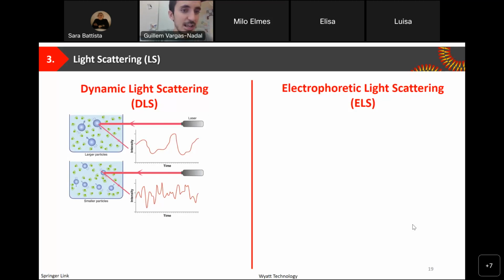First of all, in dynamic light scattering, or DLS, you have a laser with a specific wavelength, which impacts on your nanoparticles. And depending on the size of the nanoparticles, the fluctuation of the scattered light would be different. In the case of larger particles, the scattering will take more time, so the fluctuations along time would be bigger and more spread. In contrast, with smaller particles the fluctuations would be faster. Larger particles will have slower fluctuations of the scattered light, while for smaller nanoparticles the fluctuations would be faster along time.